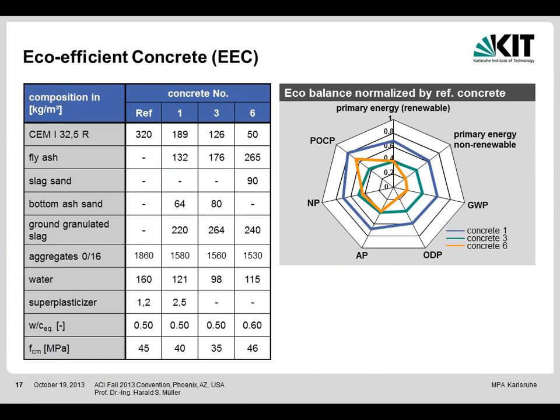And if you now do the equivalence, and I do it in a radar chart or in a spider mesh, where you have on the axis the criterion I have explained before, and I normalize it to the reference concrete. This means reference concrete would be always 1 on this individual axis. You can see that the concrete 1 is much better than the reference concrete, and the concrete 6, of course, it's clear, seems to be the best in this radar chart of sustainability.